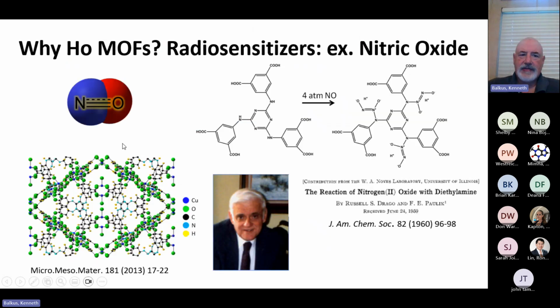Now, metal organic frameworks became interesting because we could use metal organic frameworks to bind radiosensitizers. And a good example of a radiosensitizer is nitric oxide. And so here's an example of a metal organic framework that we reported where you have this linker, and then you have these NH groups that will react with NO and form what we call a diazeniumdiolate. And then this can reversibly bind and release the nitric oxide. And so from the radiotherapy standpoint, that nitric oxide can be used to enhance the effect of the holmium. And what that means then is that you don't have to have as much radioactivity in your material if you have a radiosensitizer.